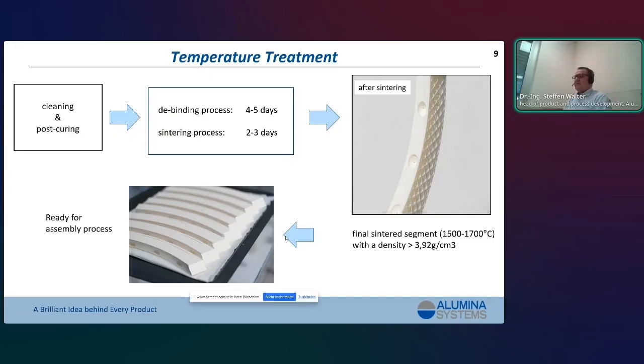Okay, so after these parts were printed, you take them off the platform. You have a special cleaning and post-curing process, and then starts the temperature treatment. The first step is the debinding process. You have to get rid of all these organic materials in such a printed part. This is the long-term process. Sometimes it needs 4 to 5, or sometimes even 6 days.